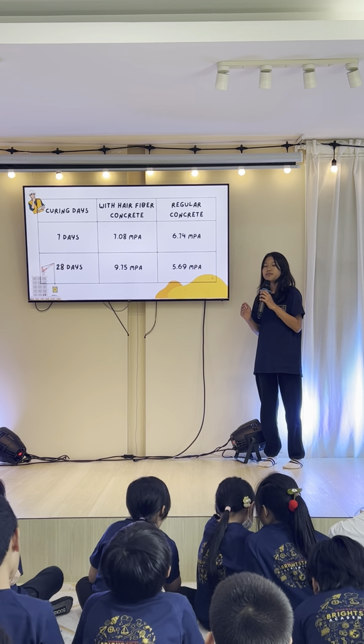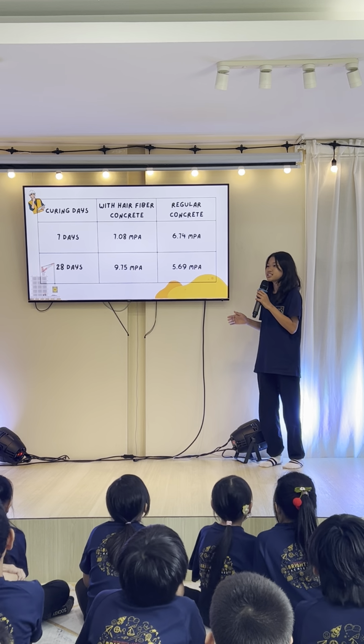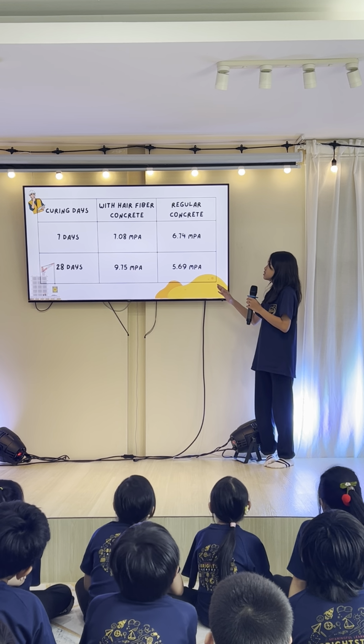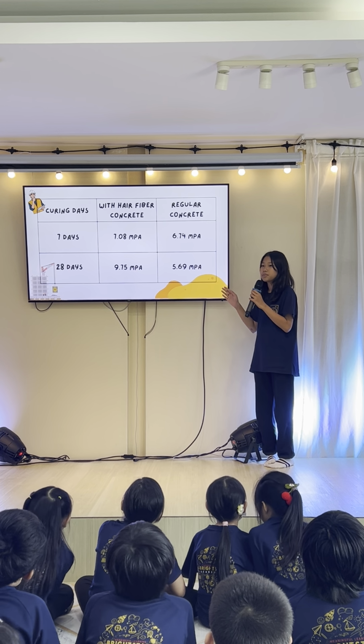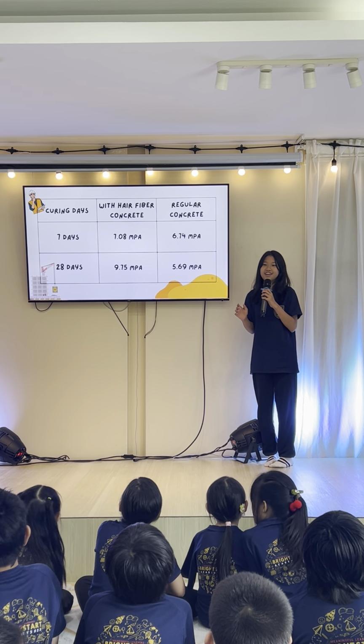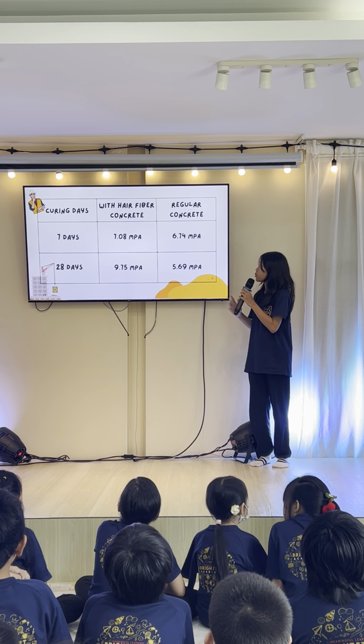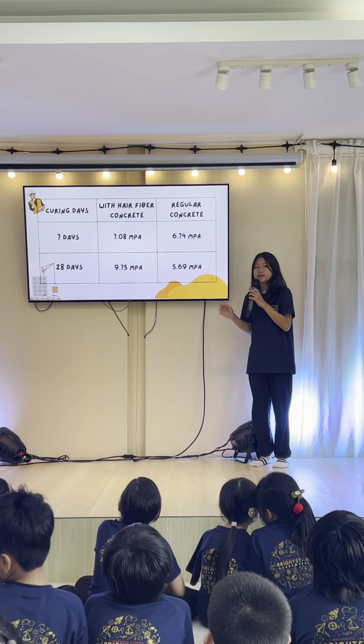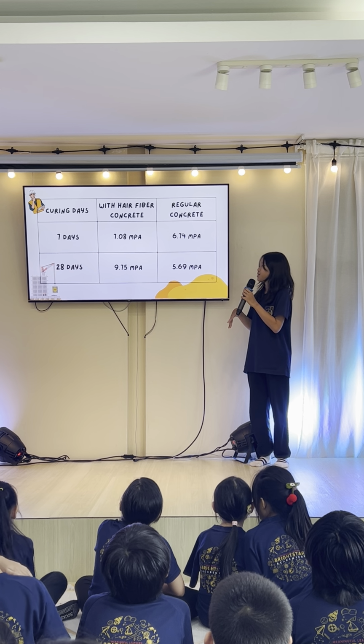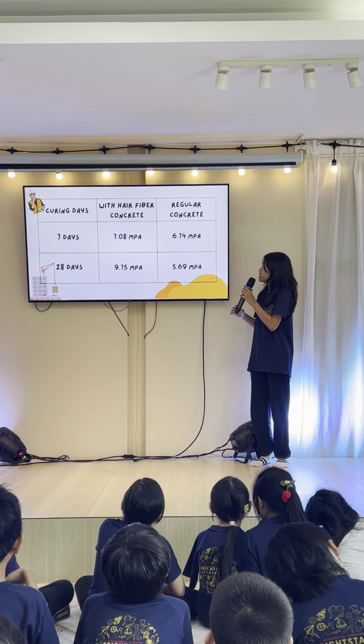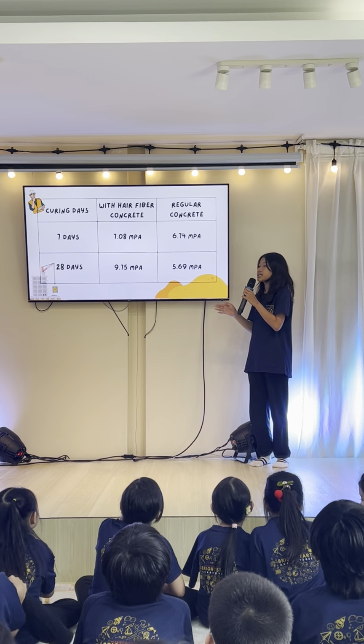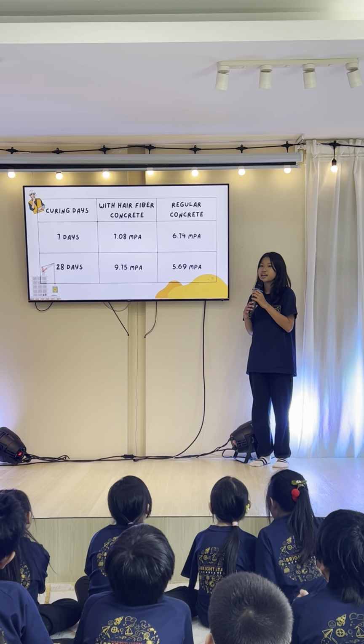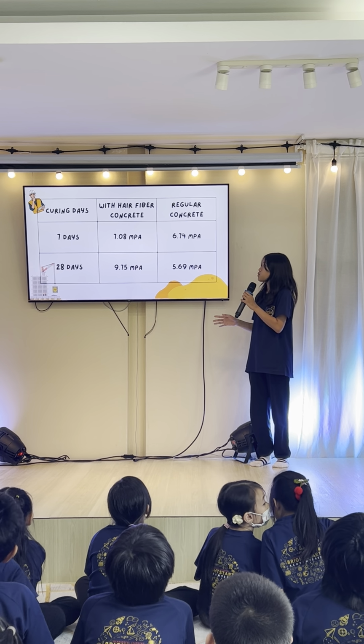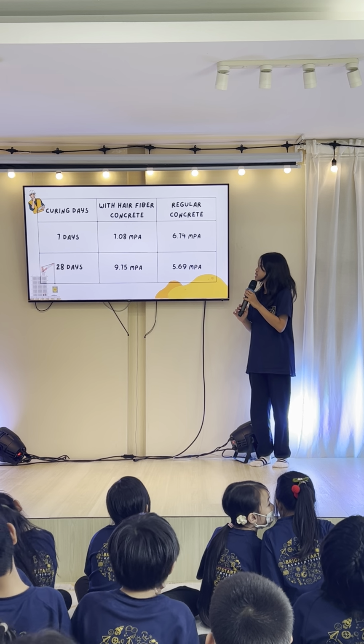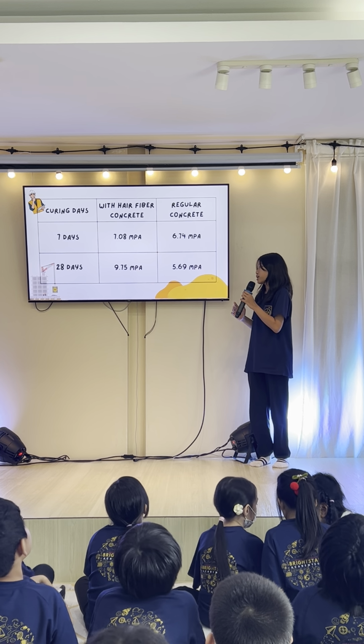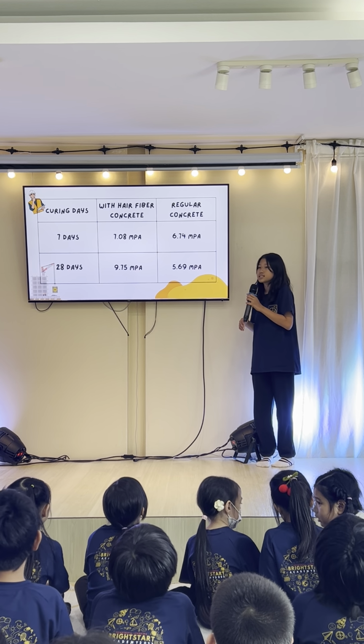This is my results based in charts. I chose to do the strength in MPa, which stands for megapascal. So for 7 days, hair fiber concrete is 7.08 MPa, and regular concrete for 7 days is 6.74 MPa. And for 28 days, fiber concrete is 9.15 MPa, while the regular concrete is only 5.69 MPa.